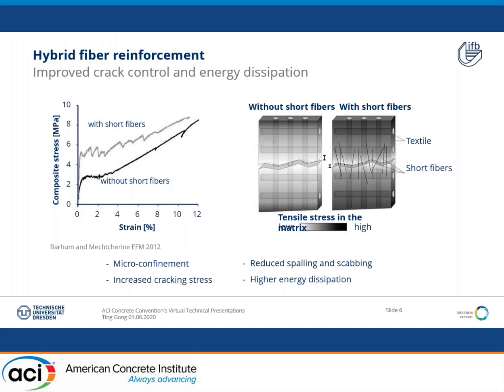With the help of the crack bridging effect of short fibers, the first crack stress can be improved and the crack width can be reduced. However, as we can see from this diagram, there's still plenty of room for improvement regarding the ultimate tensile strength or the multiple cracking propagation. So here we have a question to think about. Is it possible to further improve the hybrid reinforced composite behavior? And how about tailoring the material with the fibers or matrices that we already have?